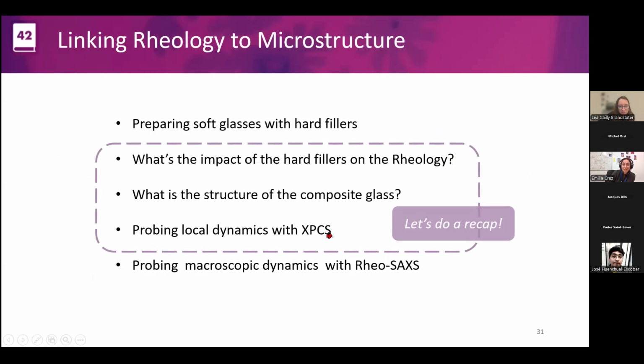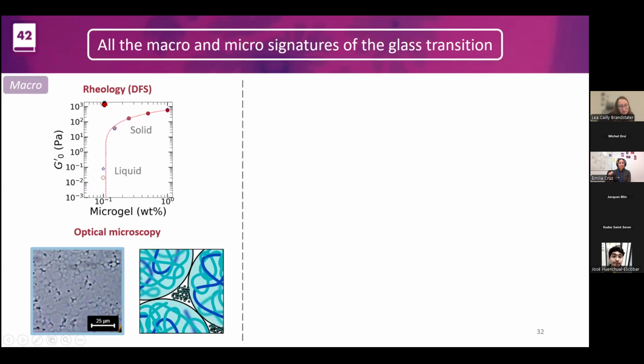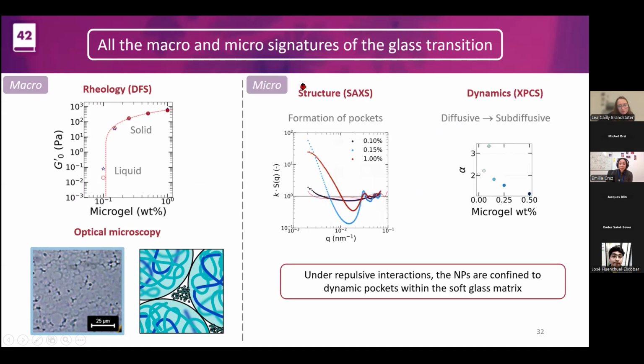If we do a little recap of this part of the talk, we now know that the macro and microsignatures of the glass transition have been revealed. So in the rheology, there was not a lot of difference when the particles were there. Also in the microscope, we were able to see that there's something that appears. Thanks to the microstructure knowledge, we know that we have revealed that there is indeed a glass transition here that's seen by just the confinement of these nanoparticles in pockets, and the dynamics go from diffusive to subdiffusive. So the particles are slowed down once they are caged in the pocket as well. So under repulsive interactions, because so far we see that there's no particular shift of the glass transition when the particles are there, the nanoparticles are confined in dynamic pockets within the soft glass matrix.